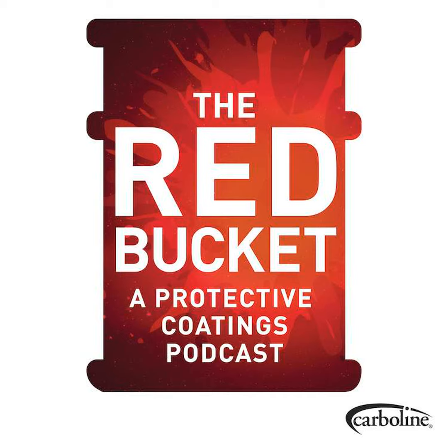So you went from having urethanes, aliphatic urethanes that weather really well, to a fluorinated urethane that weathers, frankly, better than probably any other type of material that's out there. These materials rely on a carbon-fluorine bond. That bond energy is stronger than what comes from the sun. And so it just simply doesn't break down. There's other components in it, because it is a fluorourethane, that do break down over time, but because a large portion of it is that carbon-fluorine bond, it really has a very, very, very slow rate of degradation.